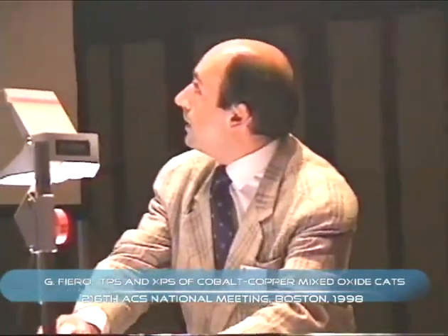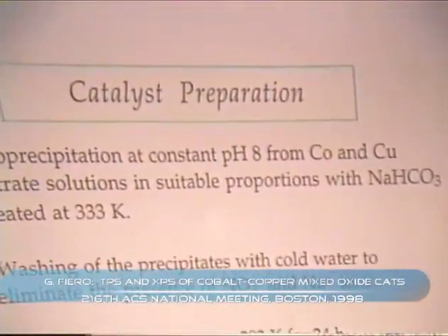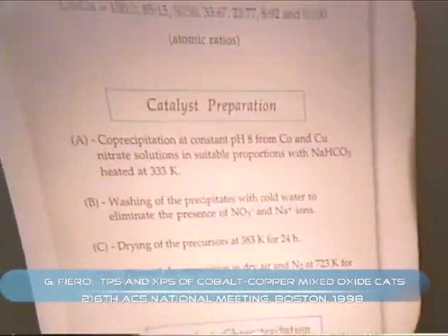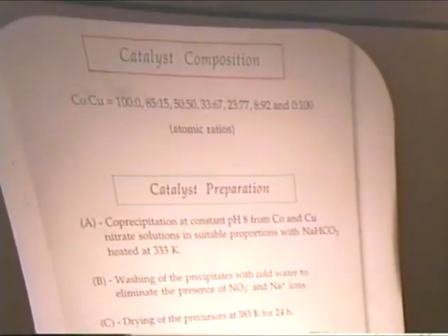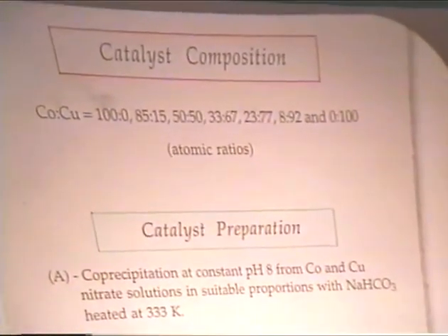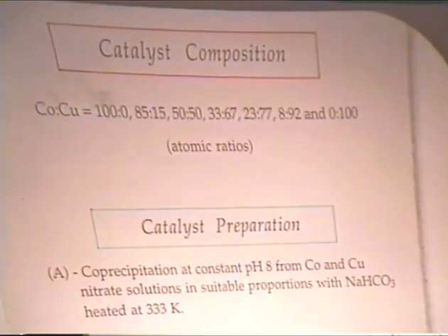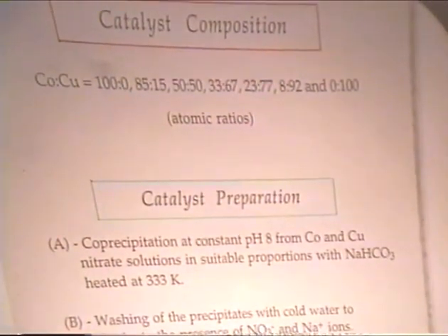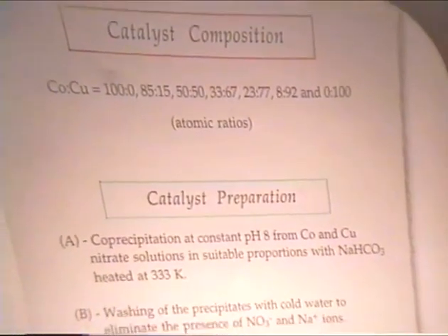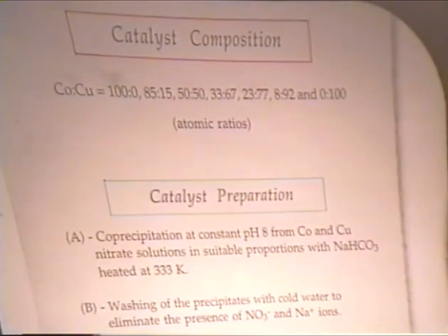We prepared the cobalt copper catalysts in a wide range of compositions by co-precipitation at constant pH. We added the cobalt and the copper nitrates to a sodium hydrogen carbonate solution, and co-precipitation at constant pH is one of the most useful methods for obtaining homogeneous precursors, namely the catalyst metal components should be present in the same crystalline structure.